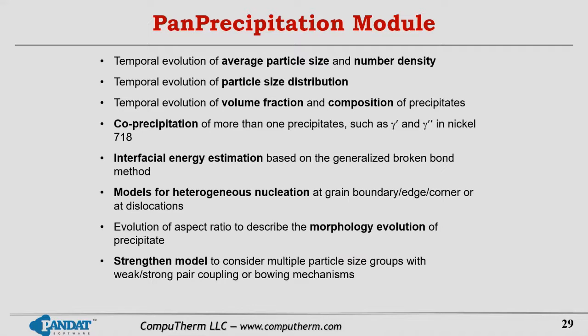So the precipitation module is designed to simulate temporal evolution of average size, particle size, number density, particle distributions, volume fraction, and so on. And we can also consider co-precipitation, like for example in nickel 718, we have gamma prime and gamma double prime. Then we can simulate the co-precipitation of the gamma prime and gamma double prime.